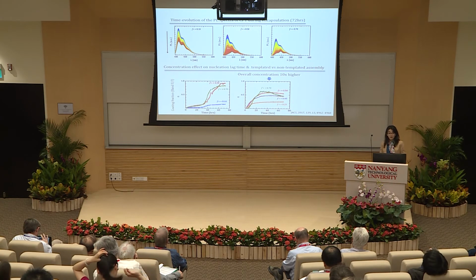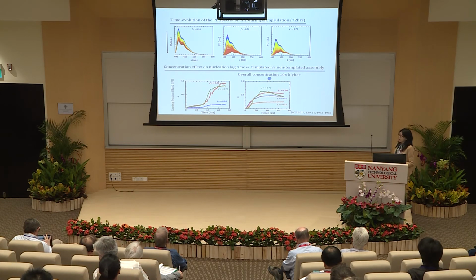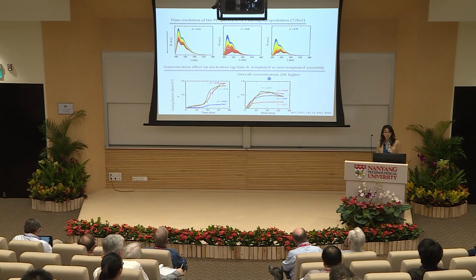And what you see is the time evolution of the fluorescence spectra of this conjugated polyelectrolyte during the encapsulation. At low charge stoichiometry, you see the binding, which comes with the quenching of the signal, but as you see, there is no stretching. At charge stoichiometry, it binds, and it also manages to stretch the polymer.